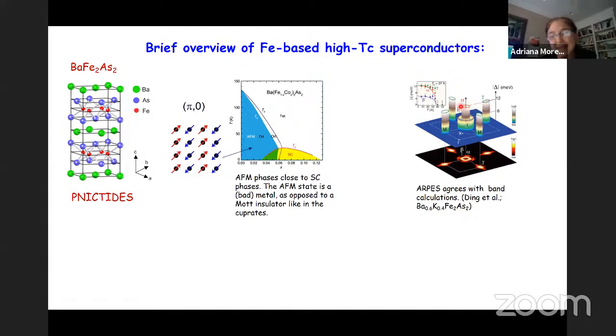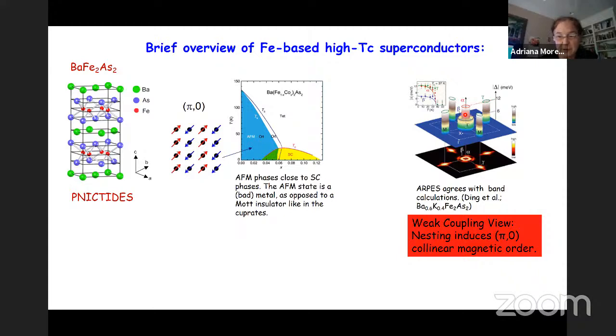The orbitals that contribute to the bands forming the Fermi surface are basically the 3d orbitals, although mainly the T2g orbitals: dxz, dyz, and dxy. Because of the nesting of the Fermi surfaces at pi0 and 0pi momentum, early on people thought these materials could be explained in the weak coupling regime, particularly because the ground state was a metal.